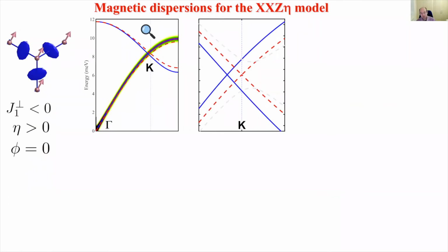And of course, we know that the XXZ Hamiltonian provides a reasonable description of the data almost everywhere except the gap. So we're looking for a gap scenario that would change things only very little in other parts of the zone. And this eta interaction actually does do that because adding it only makes very small changes between the red and blue lines here. And most changes are on the Brillouin zone boundary.